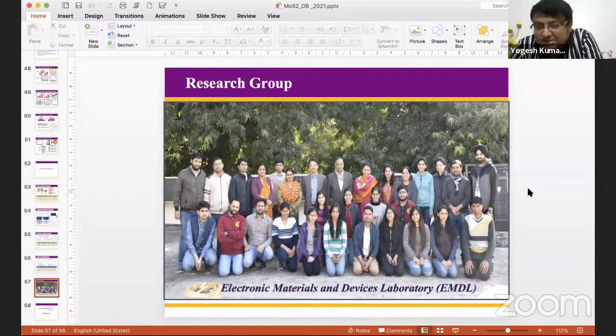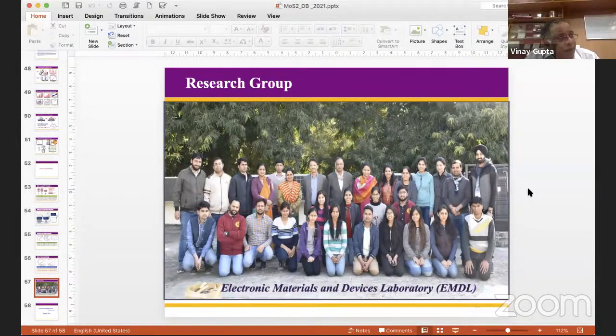Okay. So next question is from Ritvik Sharma. Is the PLD technique most commonly used among the other newly introduced methods, or is it some other method? Generally, for 2D materials, people are using the exfoliation method, where they use Scotch tape and put it on the bulk material. They remove the Scotch tape, and with it one layer comes out and they transfer this layer to the other system. But in this case, getting a continuous layer is very difficult and the quality of the material is poor. The second alternate technique which people are using is chemical vapor deposition.